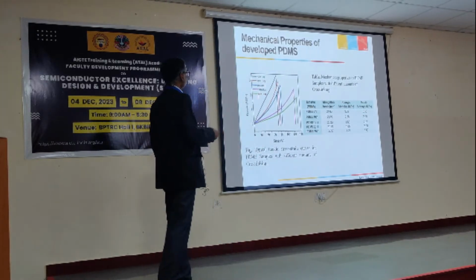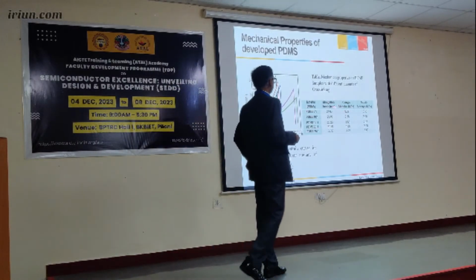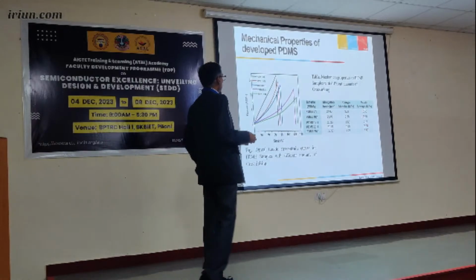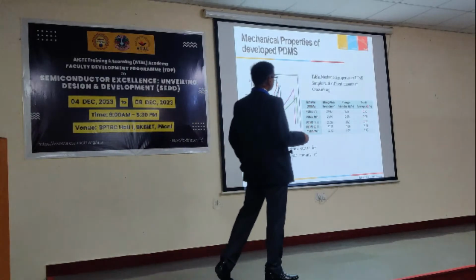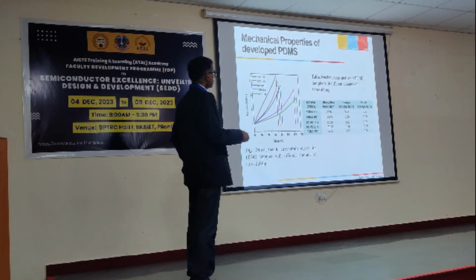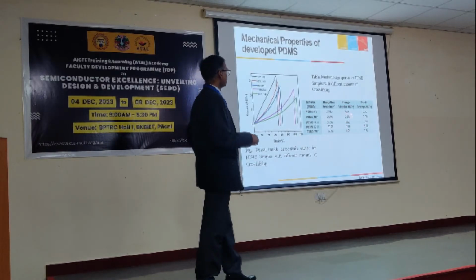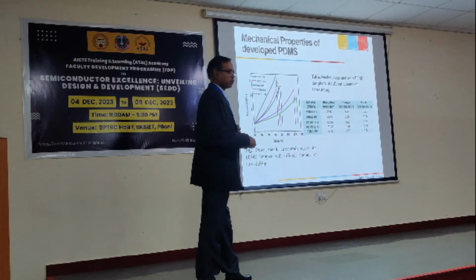Yeah, so this is the mechanical property that is shown for the different base to curing agent ratios. Here you can see that the tensile strength is 3.38 for PDMS 5:1. When the ratio is increasing, you can see that the tensile strength is decreasing. In fact, the Young modulus is reducing. The reducing Young modulus is better for the flexibility. That means it is becoming less stiff. So the stiffness is reduced, which is one of the requirements for the flexible substrate. So this is good, which is actually taking place here.